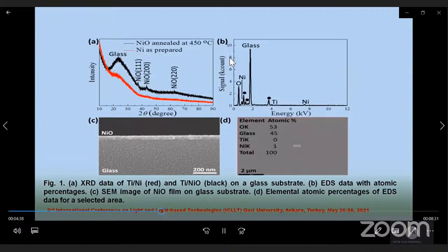From the XRD patterns and EDS analysis, no other impurity peaks were detected in the sample. Further investigation with the SEM images shown in figure 1C revealed uniform and flat thin film formation, and the average film thickness of nickel oxide is found to be 45.7 ± 4.6 nanometers. Figure 1D shows an EDS analysis area with elemental atomic percentages.